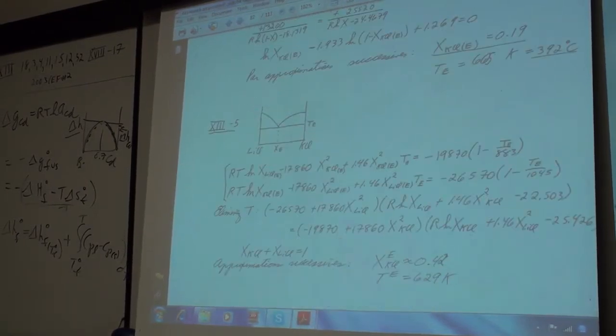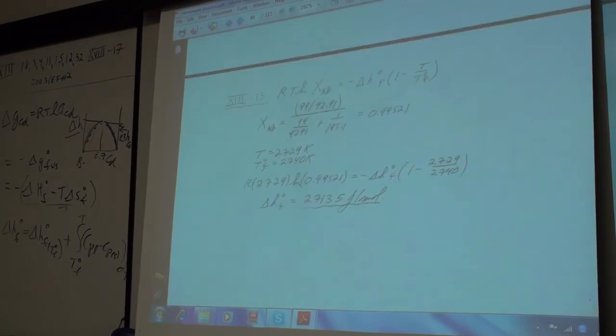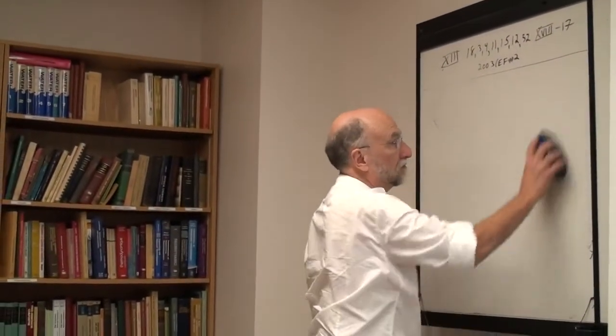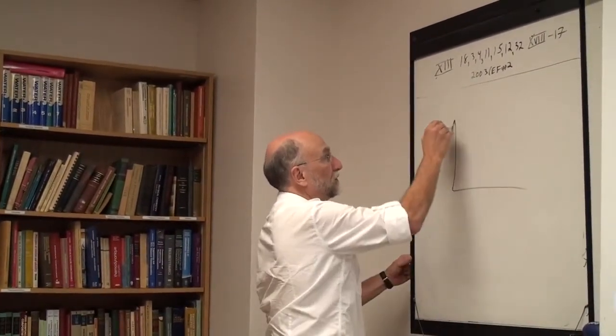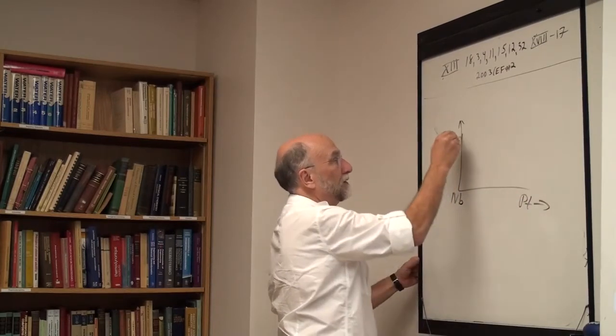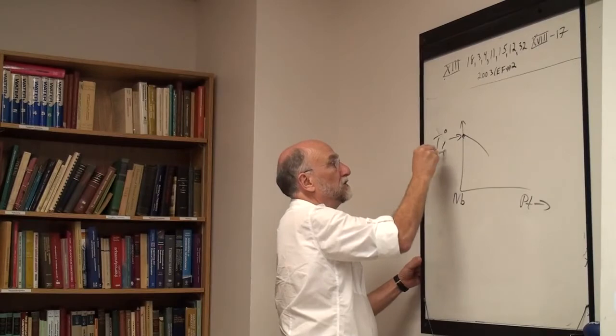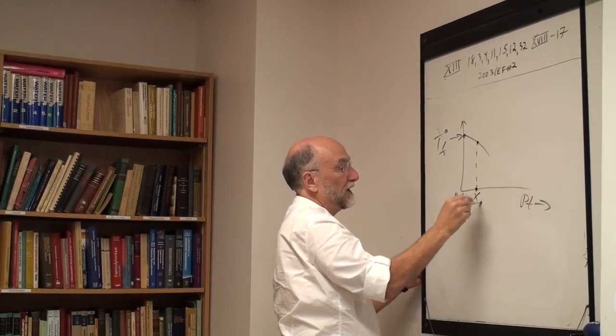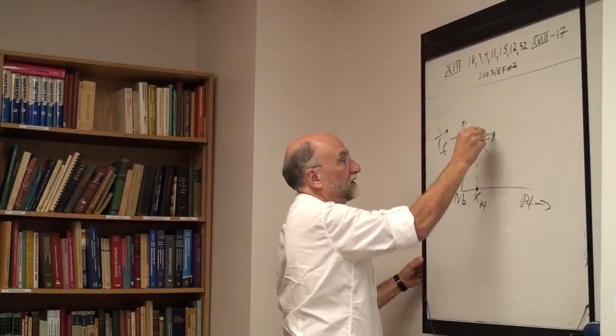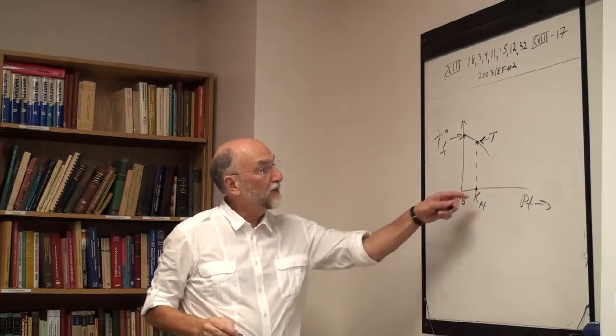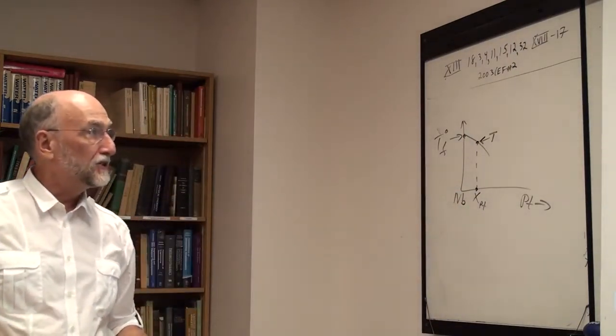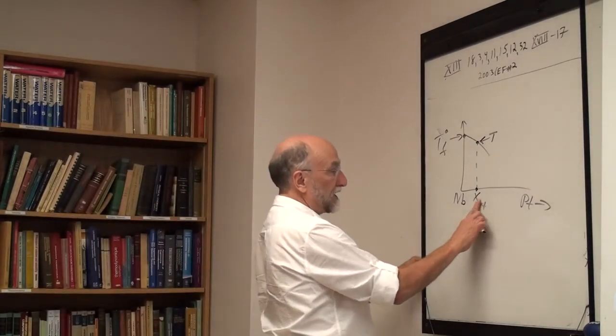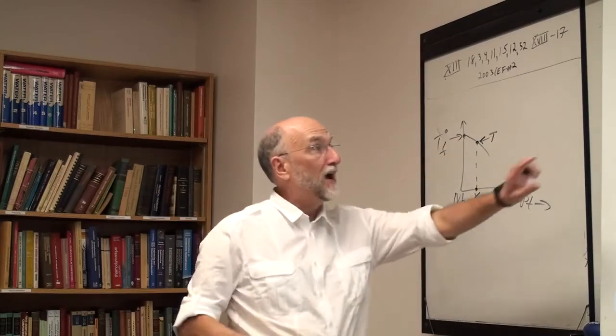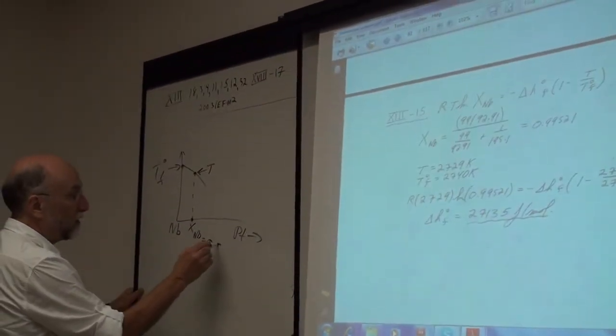Alright, so we go to number 15. So as before, here you have niobium, over here you have going to platinum. You have the liquidus temperature here. This is T naught of fusion of niobium, and this is at X platinum, which is quite small, and this is T. So you measure the change in temperature as you add a small amount of platinum. How much platinum? I measured the mole fraction. Actually, this point here is X. I converted from weight. I had 1 gram of platinum, so I converted to mole fraction. The mole fraction of niobium at that point is